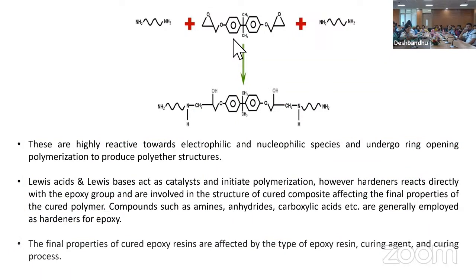So the epoxy ring, we all know, is a 3-membered ring containing one oxygen atom. During its polymerization, there is a ring opening of this ring, and diamines like ethylene diamine, which we are using here as curing agent, open the ring and a long chain polymer is obtained. This is because this small ring is very reactive towards electrophilic and nucleophilic species. That's why it undergoes ring opening reaction.